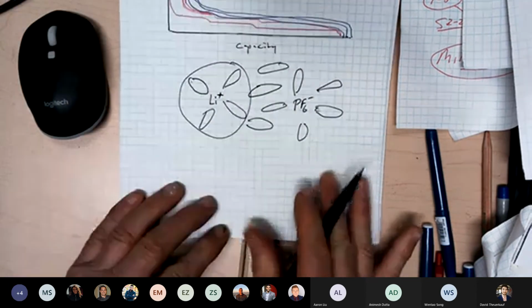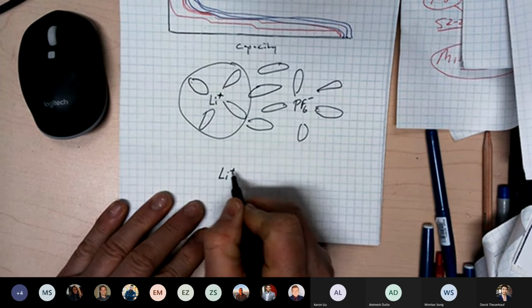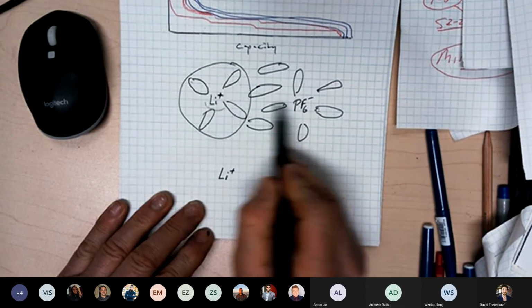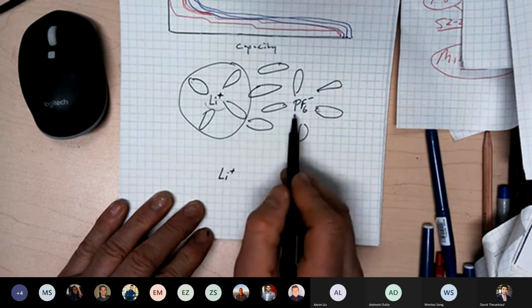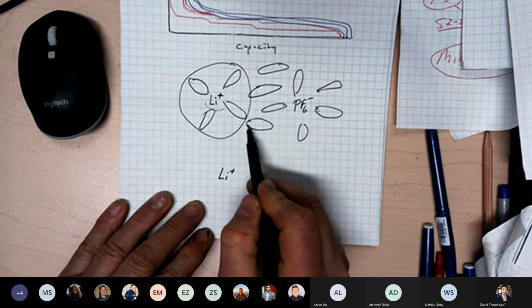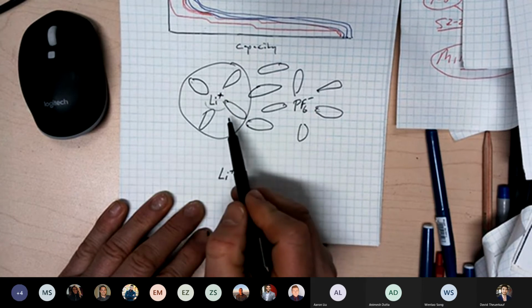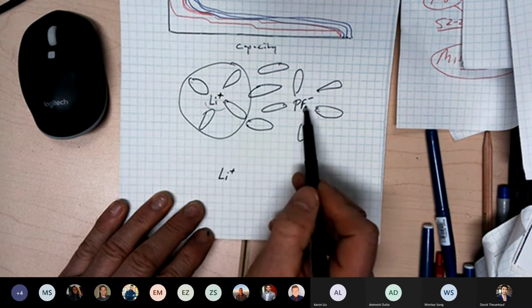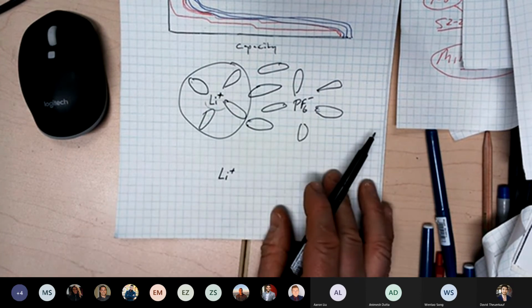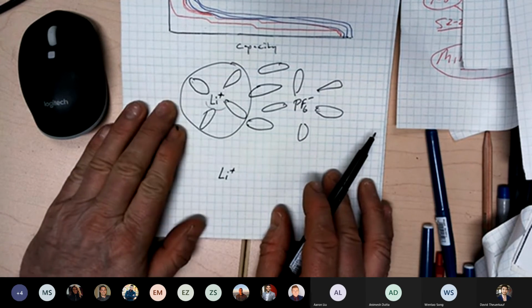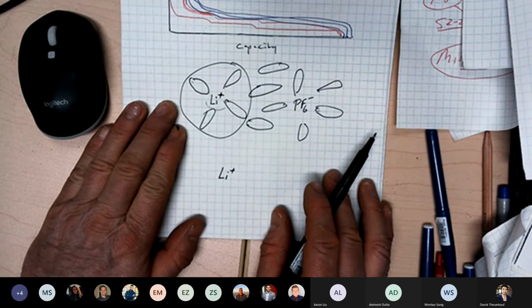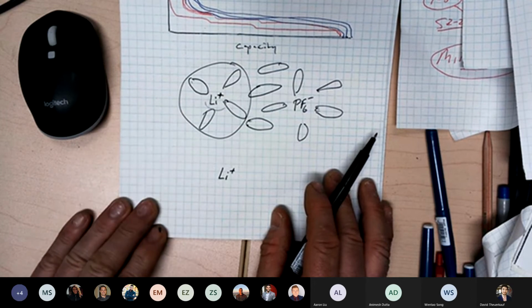But if you increase the concentration a ton, you get situations like this. That's a positive charge, and that's a negative charge. Well, they attract each other. And the reason that they're far apart is because they can reduce their energy by dissociating and being isolated like this. And the reduction in energy is quite dramatic. I don't know if any of you have ever tried to mix a large volume of electrolyte solution. If you try to mix 100 mils even, and you put the LiPF6 in the solvents, that solution's going to get hot because this heat of solvation is big.